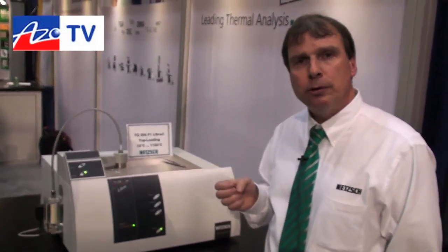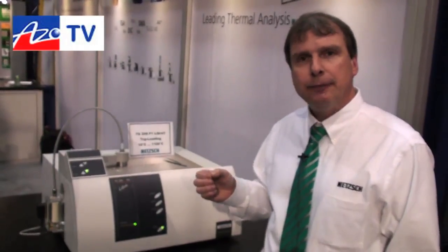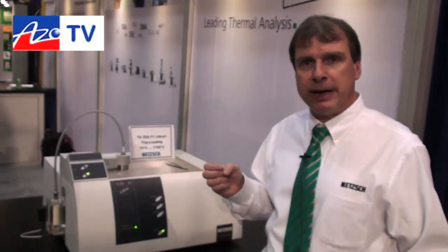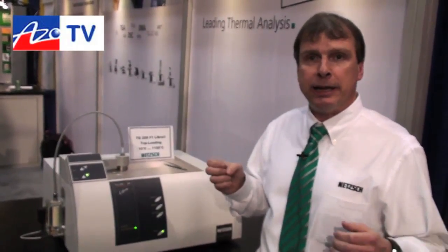We could also run an experiment under vacuum or reduced pressure if we wanted to, say, for example, separate a high boiling plasticizer from thermal decomposition in a polymer. By reducing the pressure, we lower the boiling point of the plasticizer, so it will be separated better from the degradation of the polymer. And Dave, you said the new model here has some new features compared to the previous model. Can you tell us about those?